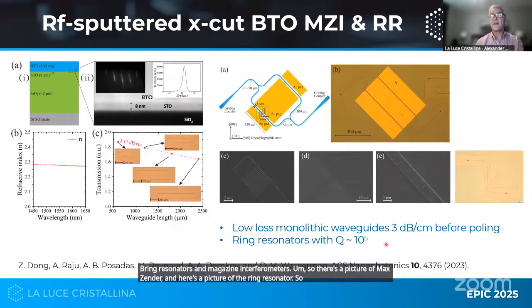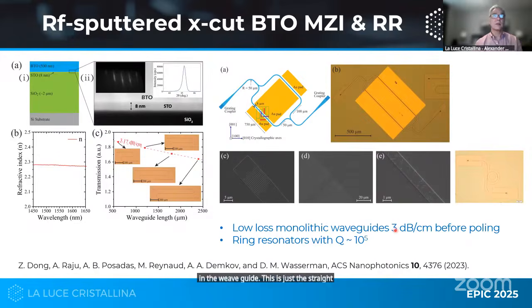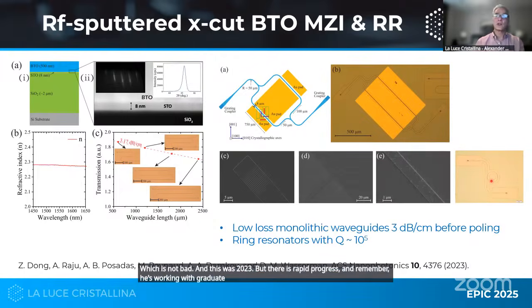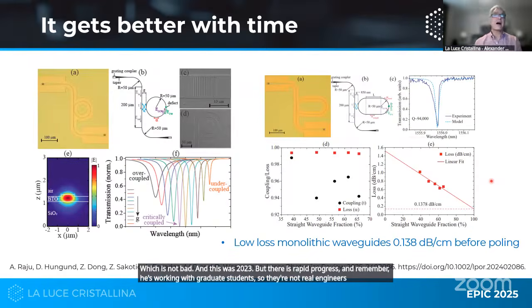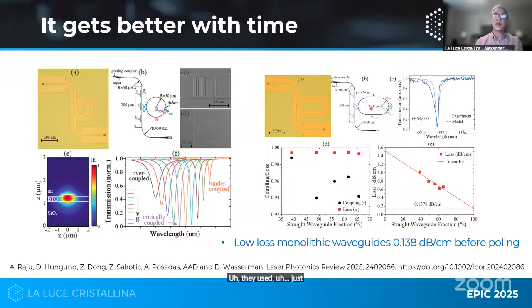So they showed a fairly low loss in a waveguide. This is just a straight waveguide loss obtained by cutback measurement right here. So you make different waveguides of different length and plot that. And they were able to get a resonator with a Q of 10 to the 5th, which is not bad. And this was 2023. But there is rapid progress. And remember, he's working with graduate students, so they're not real engineers. And so in 2025, they used just resonators, racetrack, and this is a ring resonator.